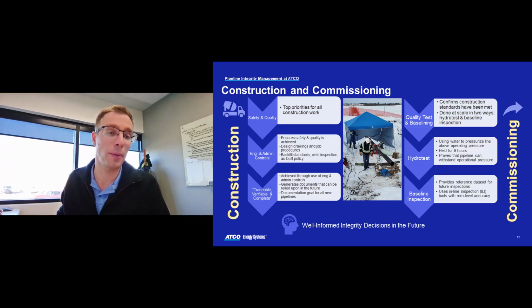This test involves pumping water into the pipeline and pressurizing it to a point higher than the maximum operating pressure of the pipeline. This test is considered successful if the pipeline can hold that pressure for at least 8 hours. If the pipeline can maintain this pressure without incident, then no existing construction or material flaws present at the time of the test are expected to fail under normal operation.